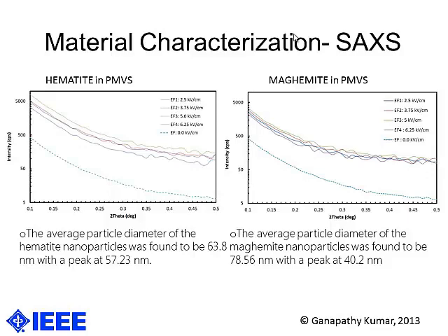So, with increasing applied electric fields, we noticed that the scattering intensity increased up to a point, and after a point it just came down. So at up to 5 kilovolts per centimeter, we noticed that the scattering intensities increased, and at about 6.25 kilovolts per centimeter, the scattering intensities came down. We tried electric fields up to 7.25 kilovolts, and at 7.1 kilovolts, we had an electrical breakdown of the system of the composite itself.